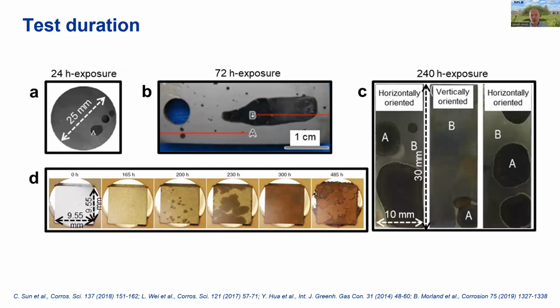In terms of test duration, there's an issue here for people to be aware of: the incubation time for dissolution of the liquid water in dense phase CO2 is actually quite lengthy. It can take up to a day or sometimes even 2 days, depending on the conditions, for all of the liquid to dissolve in the CO2. And that means that if you don't wait long enough for that to happen, you're not carrying out the test under the conditions that you expect.